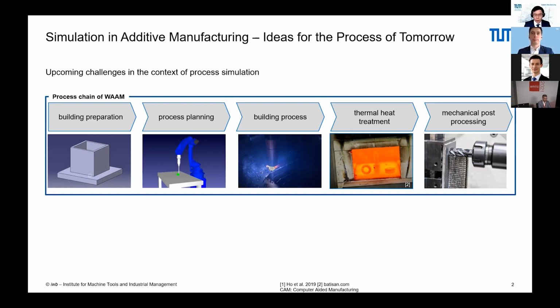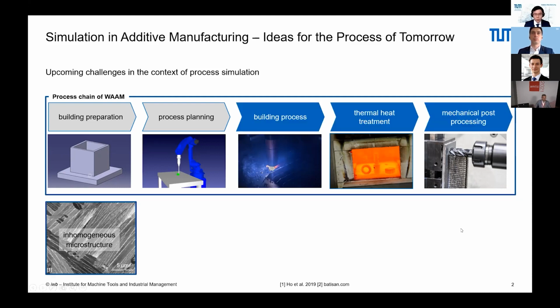We have identified some main challenges we face in industrializing WAAM, which can each be attributed to certain steps of the process chain. For one, we have an inhomogeneous microstructure. We know that the microstructure significantly determines mechanical properties, and the material is only as strong as its weakest link. Therefore, we have an interest in keeping the microstructure homogeneous and also predictable.